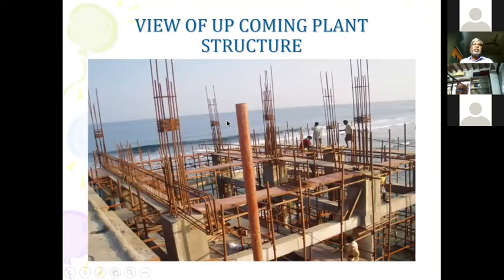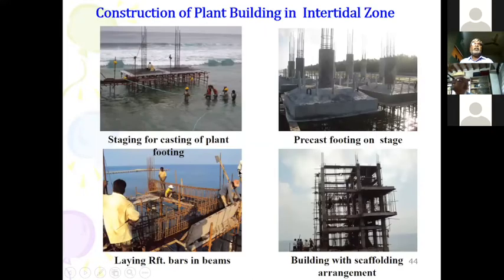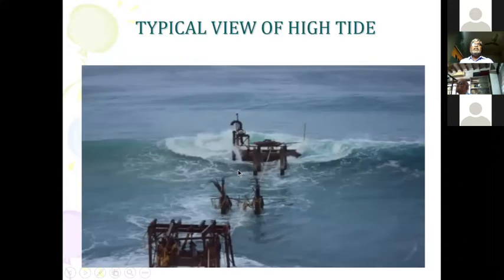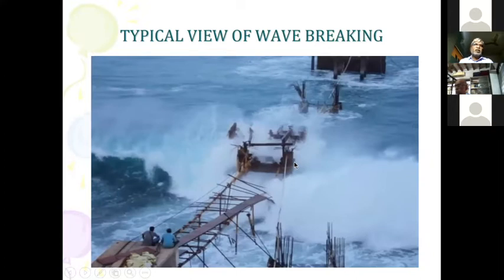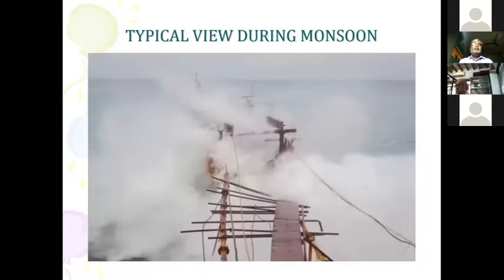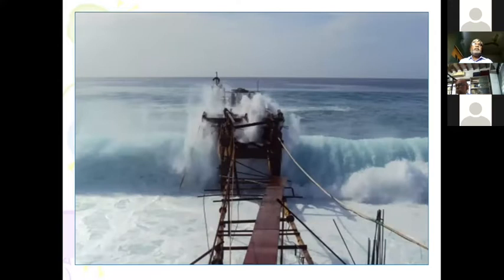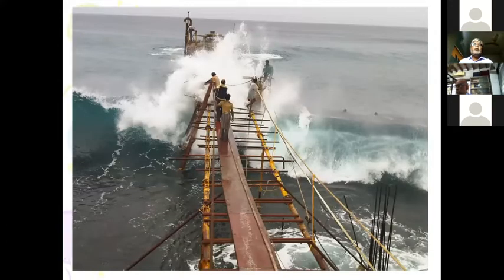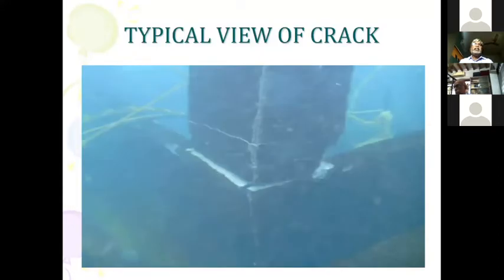This is a modeling of the plant structure. This is a plant structure which is under construction. Here we don't have much of an issue because it's not under the wave breaking zone. And once everything is over, and this is a high tide level, we removed these steel sheets all around it, and then we wanted to go with the further construction of this column height to match the level of your girder. We found that during the monsoon, heavy forces were there, but of course this was already taken into design consideration.